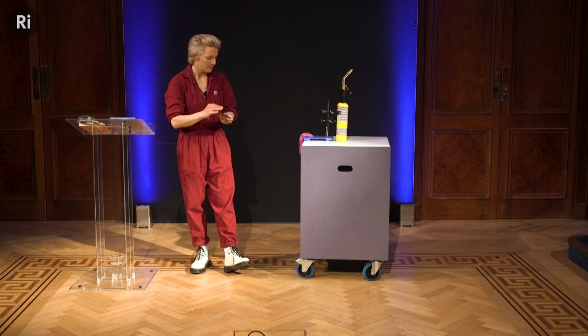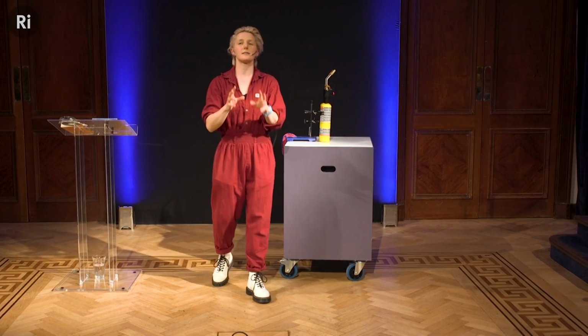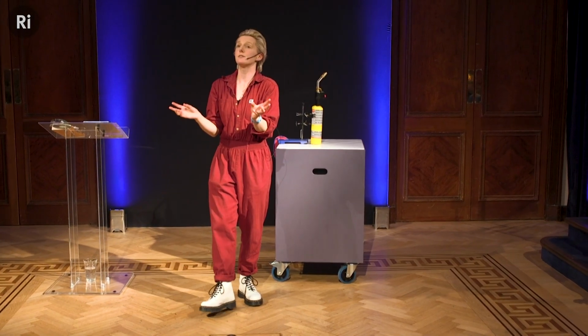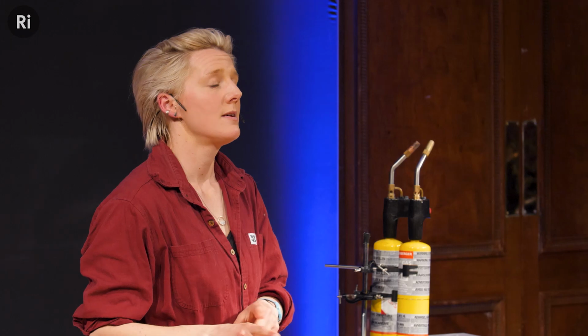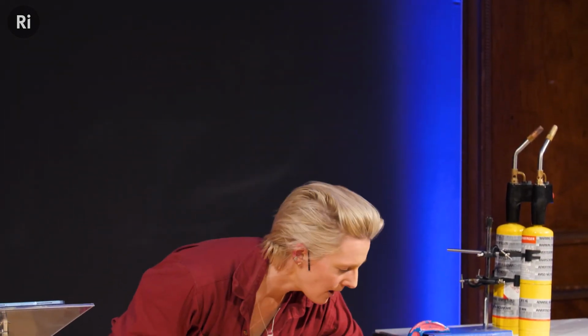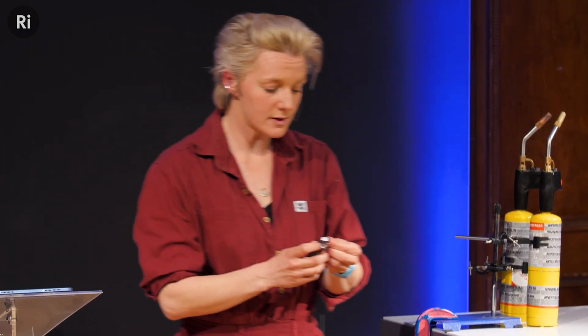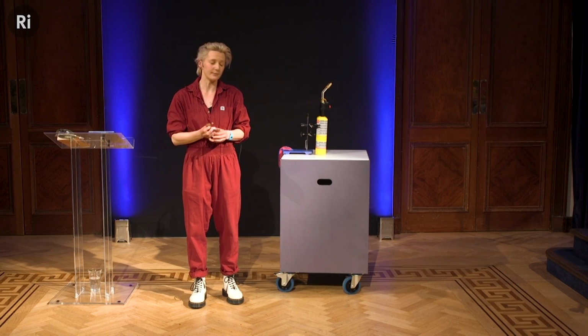So that's a mystery. That was really weird. Why did one of these pieces of steel, identical materials, one break like ductile fracture and the other like brittle fracture? Well, there's two possible explanations. The first is temperature. Because if you break what are normally ductile materials when they're extremely cold, they go through what is called a ductile to brittle transition.